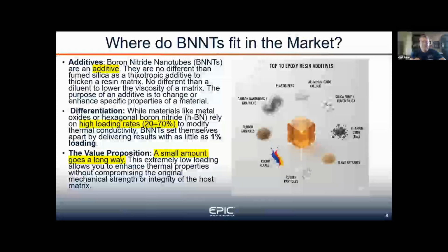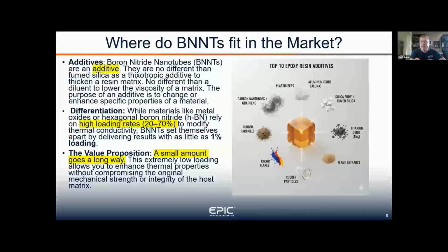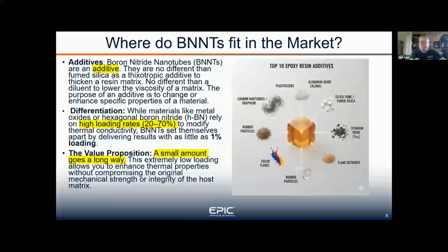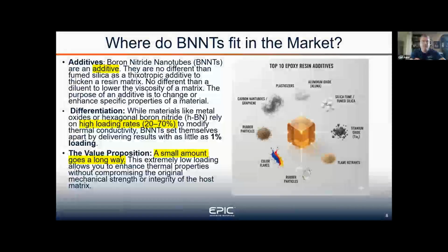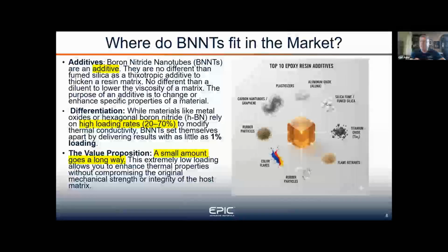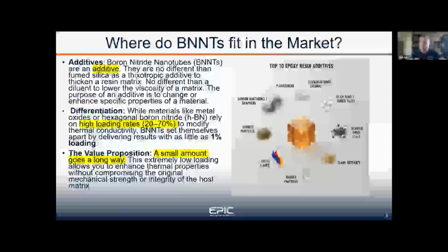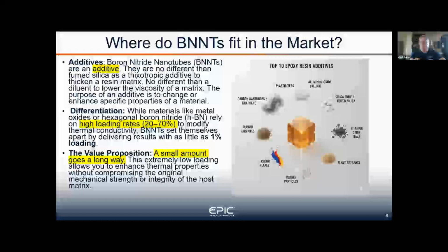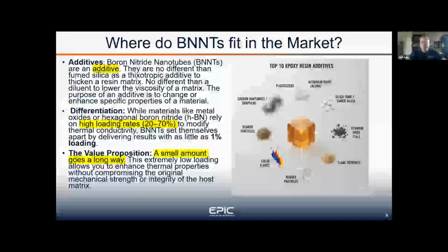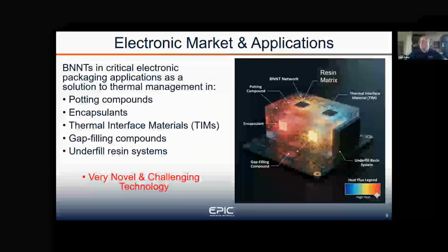What are BNNTs? They are an additive. What differentiates them from regular fillers that help with thermal conductivity is that they provide great results at a very low loading. So instead of 20 to 70% of metal oxides or hexagonal boron nitride, the value proposition is a small amount goes a very long way.